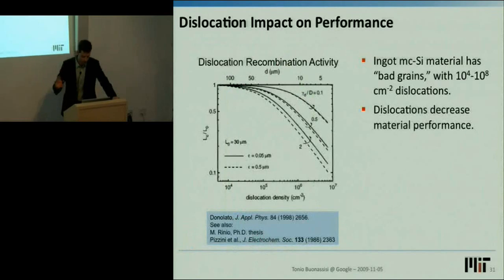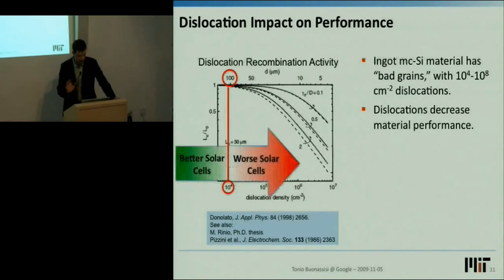Now, to illustrate that in a more scientific form, we have performance on the y-axis and dislocation density on the x-axis here. As you increase your dislocation density, your performance comes down. We have some magic number here where we have better solar cells with lower dislocation densities and worse solar cells above. If you get down to this number, 10 to the 4 per square centimeter, then solar cell performance is not really influenced much